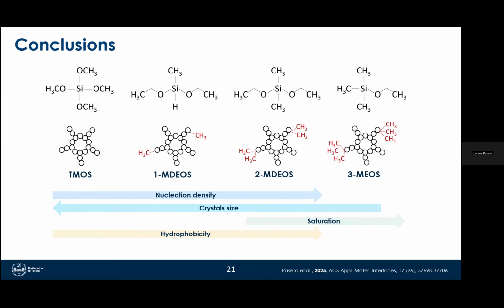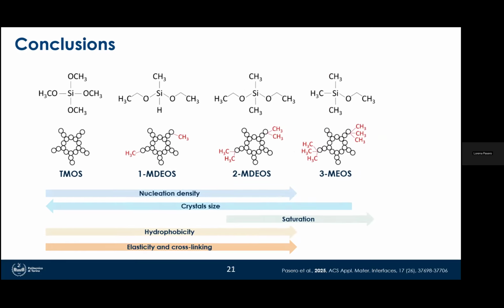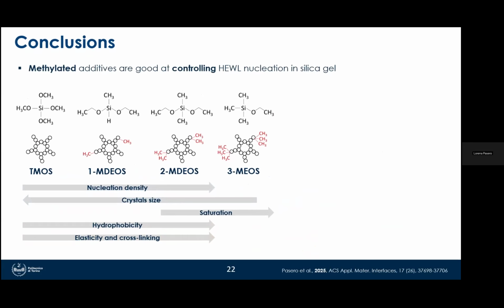Also, we looked at the hydrophobicity of the gel, which increased up to the methylation, and this was coherent with the theory that this methylation could reduce the interaction between protein and the gel. And it also increased the elasticity and cross-linking of the gel itself. However, we also demonstrated that